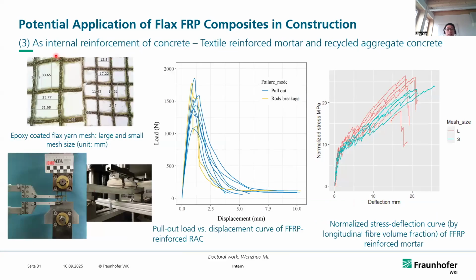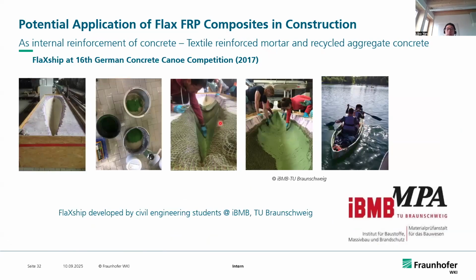Another application is internal reinforcement of concrete, as textile reinforced mortar or textile reinforced concrete structure. So we use the epoxy-coated flax mesh as the internal reinforcement to increase the load carrying capacity of the concrete and to modify the crack distribution of the concrete. This is an interesting example of using the flax mesh to develop the textile reinforced mortar, the so-called flax ship at the German concrete canoe competition with our students.